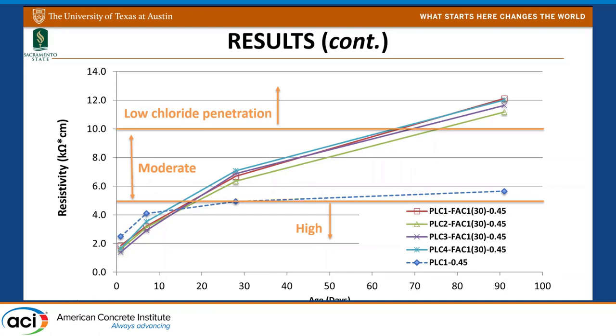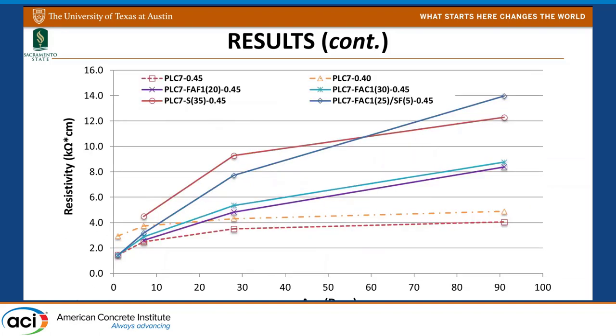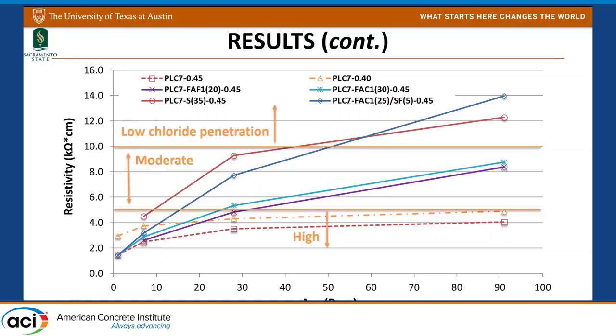We got the same results for the second cement plant. The control mix at 0.45 w/c was our baseline, and reducing to 0.40 increased resistivity but not significantly. However, once we added SCMs — especially slag, which is very effective at refining porosity and decreasing permeability — we would expect low chloride penetration for these mixes, indicating more durable concrete. That summarizes the mechanical properties and resistivity results.